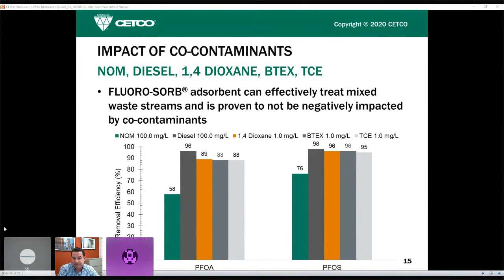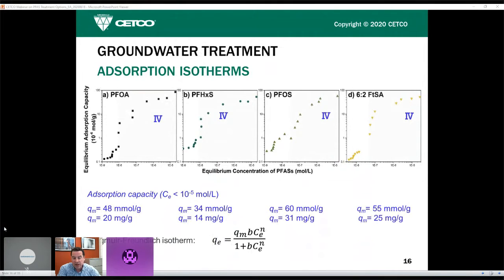Next slide, please. So this is the isotherm. This is an interesting feature of FLUORO-SORB. Typically for isotherms, you see a linear response with the dosage of the media into a groundwater sample. But for FLUORO-SORB, you see this sigmoidal curve.